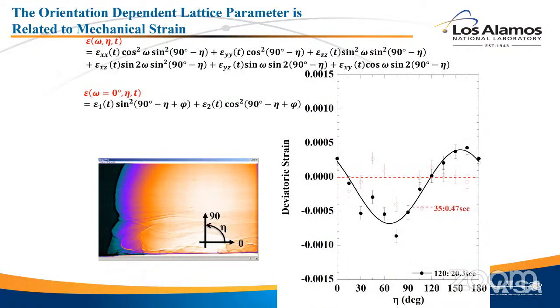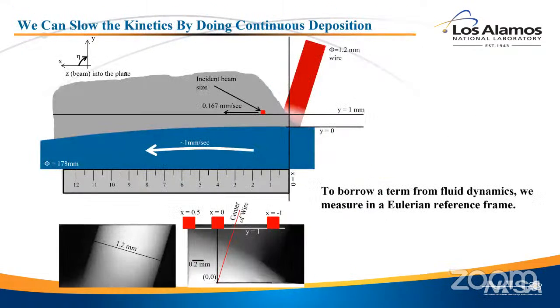Let's get through this in the interest of time. As I said, the kinetics of the experiment we're doing here were actually still too fast for our measurement technique in 2017. That's actually changed. Detector technology is exploding because the X-ray fluxes are driving the detector technology because they're so fast now. So if you did this measurement now, the detectors can measure at sort of 250 to 500 hertz, where we were looking at 10 hertz 4 or 5 years ago. So what I'm going to say isn't necessarily true, but there's always faster kinetics, so it's still relevant.